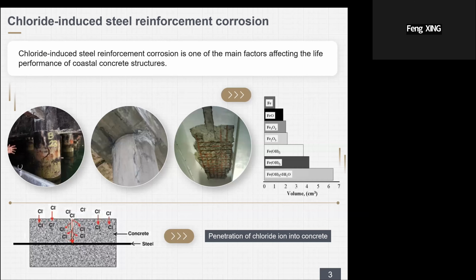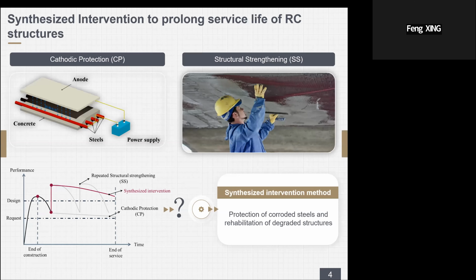The background is well known: the corrosion of steel rebars due to chloride is the most important problem for the durability of reinforced concrete structures, especially in the coastal environment. Many methods have been developed to improve the durability of reinforced concrete. Generally, the electrochemical methods, such as cathodic protection, can prevent steel corrosion, and structural strengthening, which is most familiar for civil engineers, can improve the mechanical behavior of degraded structures. However, structural strengthening cannot fundamentally prevent steel corrosion. Therefore, the degraded structures may need repeated intervention through the service life, as shown in this curve.